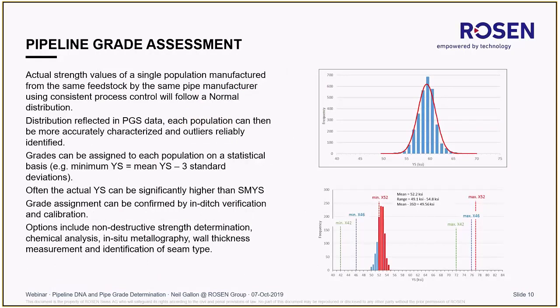Within the different populations, we can also go through and assign the pipeline grades. The way that we do this is we know that if you get a single population from the same feedstock by the same manufacturer using a consistent process, then the distribution of strength from that population will be a normal distribution. That distribution is reflected in the PGS data, so we can characterize each population accurately and reliably identify any outliers. If there's a large enough population, we can also assign the grade with a fair degree of confidence using the -3 standard deviations basis.